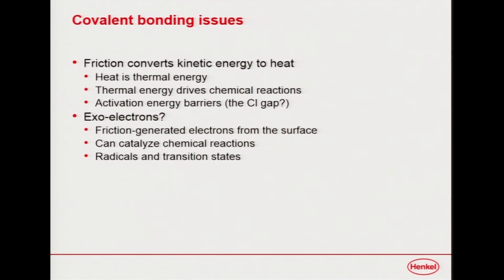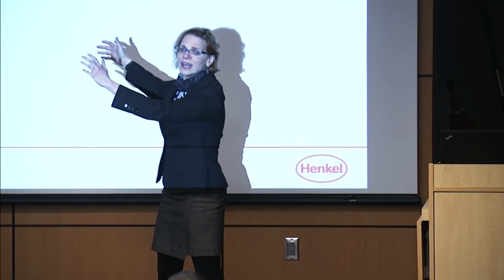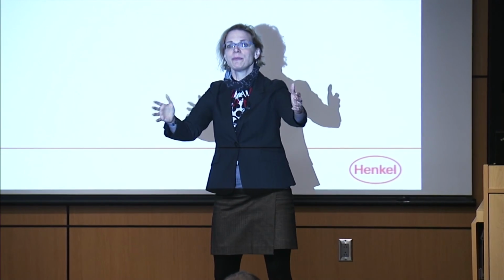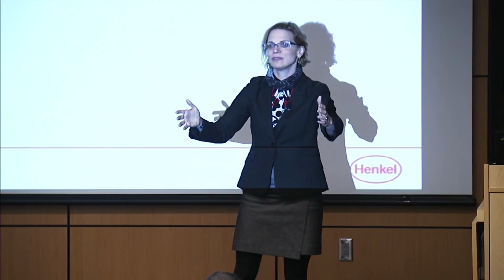We know that. We know that there are activation energy barriers. There was this incredibly challenging question in lubrication science for many, many years. We called it the chlorine gap. The chlorine gap was the fact that chlorine worked as an extreme pressure agent at an unbelievable temperature and pressure range. But phosphorus only worked at low temperatures and pressures, and sulfur only worked at really, really high temperatures and pressures. There was this gap in the middle that you could only fill with chlorine. Everybody said, why is that? Why doesn't everything just work? Well, it's never that easy.